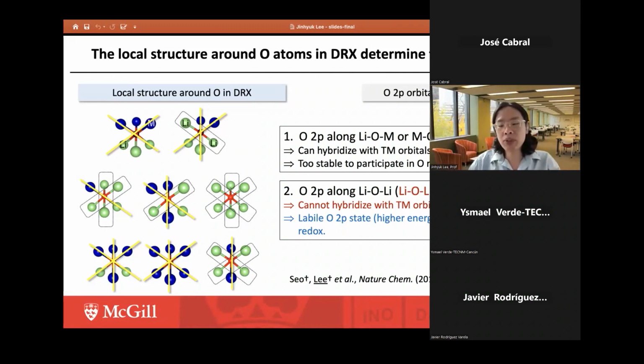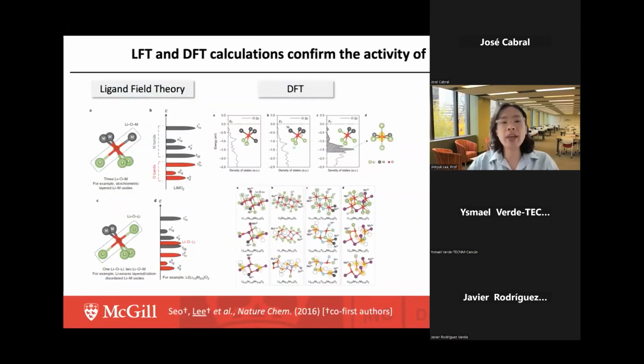Based on this simple chemical intuition, combined with ligand field theory and density functional theory calculations, which I'm not going to detail, what we found is that indeed these oxygen 2p orbitals along this lithium-oxygen-lithium state are the oxygen electrons that participate in the oxygen redox process to give extra capacity beyond the transition metal oxidation capacity, so that we can